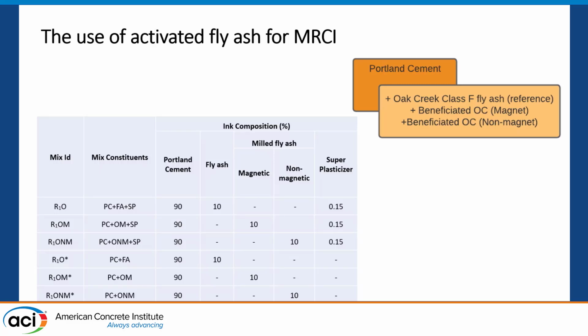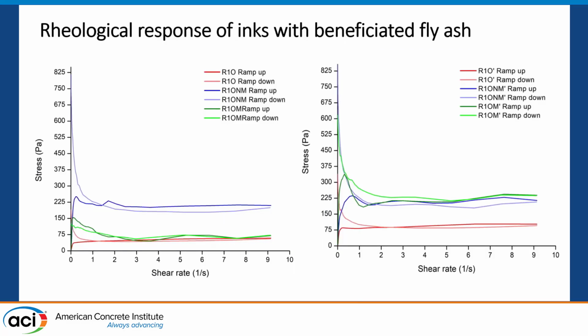We ran an additional experiment with fly ash, just 10% replacement, magnetic ash and non-magnetic ash, mainly with superplasticizer, but also non-superplasticized mixtures. What we realized is that the non-magnetic ash was actually providing a better yield and stiffening as well, because of ultrafine particles. But magnetic ash was not as reactive without a magnetic field. As soon as a magnetic field was applied, the response was very similar. The non-magnetic particles were not affected by the magnetic field.